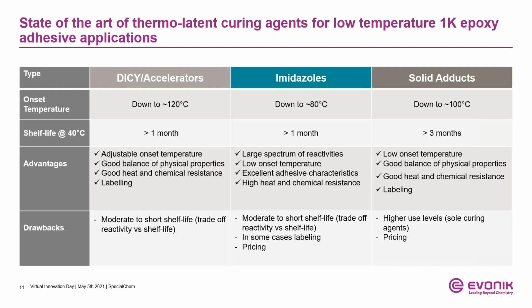When talking about low temperature curing 1K epoxy adhesives, which in principle means a curing temperature of 140 centigrade and even lower, there are basically three core technologies that enable the implementation of such systems. On the one hand, we have well-established systems such as Dicyandiamide, in combination with accelerators, which are capable to reduce the usually high activation temperatures of Dicyandiamide decisively. And these systems stand out due to their comparatively low price, well-balanced material properties, and usually they have a non-critical labeling. The onset temperatures, which can be achieved here, are around 120 centigrade and sometimes also lower, but with the drawback of usually significantly reduced shelf life capabilities.